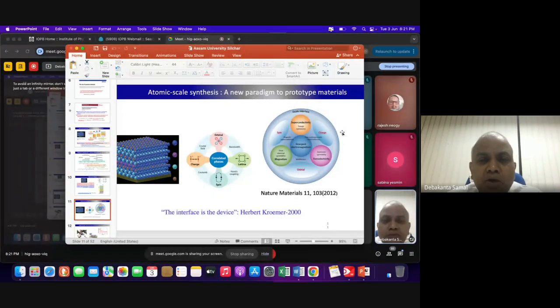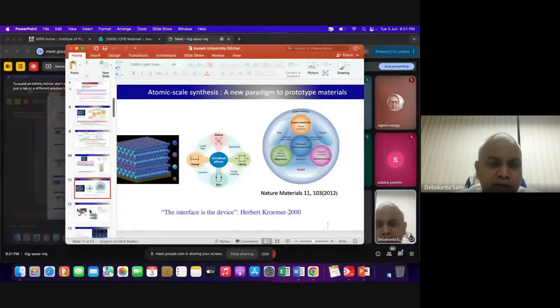As I mentioned, this is the oxide interface. I told you the electron has charge, spin, and orbital, and atoms are put in a lattice. All of them interact with each other. There is an interplay, and then you get correlated electron phases. People have seen that because of the interaction between spin, orbital, and charge, you can have magnetism, superconductivity, ferroelectricity, and emergent electromagnetic phenomena. So the oxide interface, the atomic scale synthesis I talked about, gives rise to various new emergent phenomena.